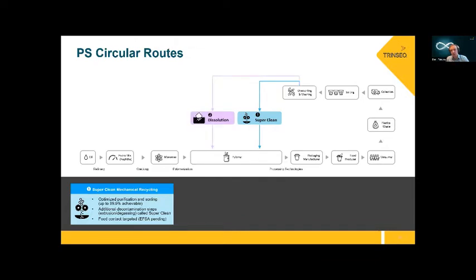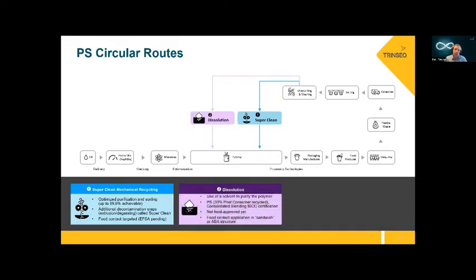Another mechanical recycling idea would be through dissolution. What you do here is you add a specific solvent that then dissolves the polystyrene into a viscous slurry, which we can then feed into our polymerization tanks. With this route, you can achieve up to 30% post-consumer polystyrene that we can add. Remember, again, it's a fairly viscous slurry. It's quite difficult to add more from a technical point of view. Also here, at this moment in time, it is not yet food approved, but we achieve similar purities, and this is used, I'll show you an example in a second, in a non-critical food application.